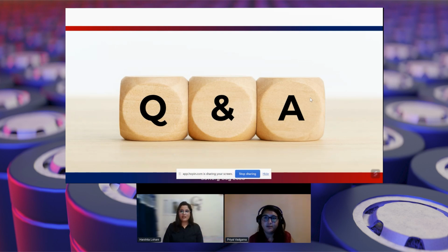Yes, definitely. As I said, the current state of the art anode is hard carbon, and everyone knows that hard carbon has an issue of poor initial Coulombic efficiency, and the interfaces that get formed on the sodium ion cathode and anode side are also unfortunately not very stable. So there are definitely issues with balancing of the full cells, but if we can have some technology like BYD is using right now, like the pre-lithiation studies they are doing on the silicon anode side, they are able to make a balanced lithium-ion full cell. So if those types of strategies could come up in the future, then definitely the cell balancing problem can be sorted out.